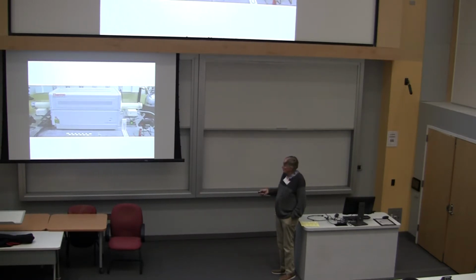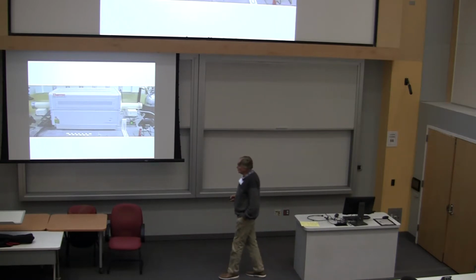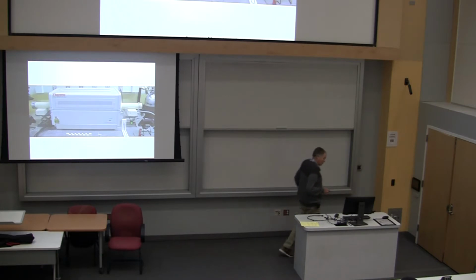And this is an example from Priscilla Rosa at Los Alamos. So this is about a 3-inch tube here. It turns out that it has these supports on the end. If you don't do this, there's a real problem with thermal sag if you go to high temperatures. The idea with this molybdenum furnace is that you can go to temperatures comfortably above 1500 degrees. You can work them up to at least 1650.